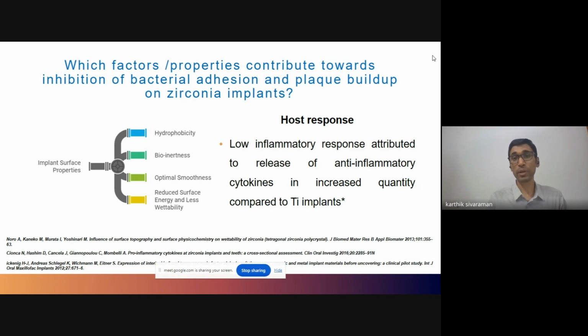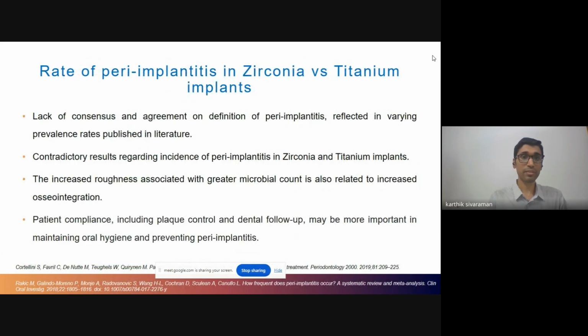But importantly, we need to look at the host response as well. The studies have documented a low inflammatory response, which is attributed to release of anti-inflammatory cytokines in increased quantity compared to titanium implants. So you have a situation whereby there is less tendency to accumulate plaque, less tendency for bacterial adhesion, ingression, progress, and also a less inflammatory response on part of the host or the body. So this should logically lead to the conclusion that you see less peri-implantitis or less prevalence of peri-implantitis compared to titanium implants. And that would definitely be in agreement with what has been observed in the preclinical studies or in vitro studies as well.